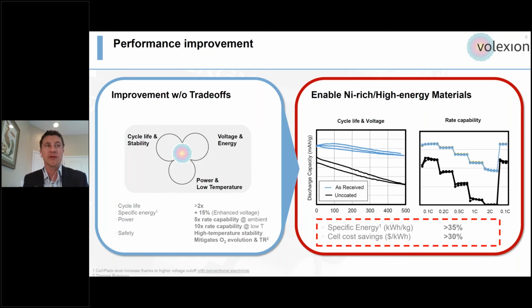But one value that's of high interest for the industry right now of our technology is to enable the next generation of cathode materials, which are very high in nickel and low in cobalt, which drives both a very high energy density, but also creates a lack of stability in the crystalline structure of the cathode material. And hence these materials, such as lithium nickel oxide, for example, need a stabilizing solution such as our conformal graphene coating to be safely introduced commercially at scale. And by introducing these high energy materials at high voltage, we can drive 35% energy density improvement at the battery level, and hence drive 30% cost savings, which is a significant improvement.